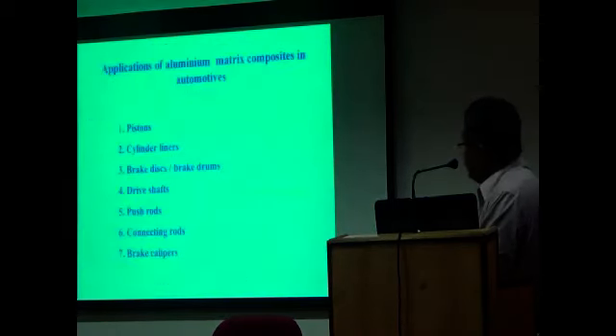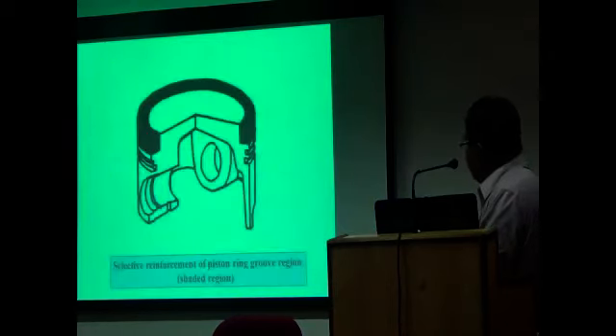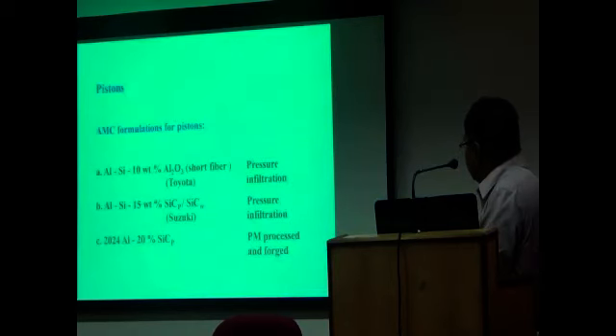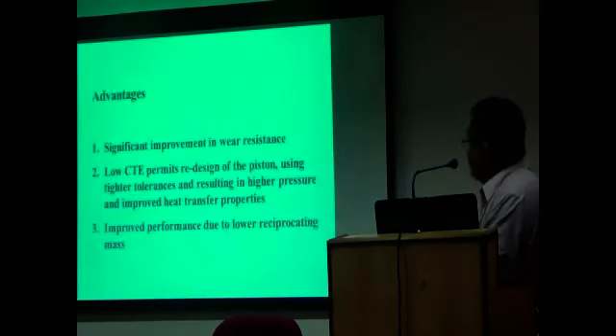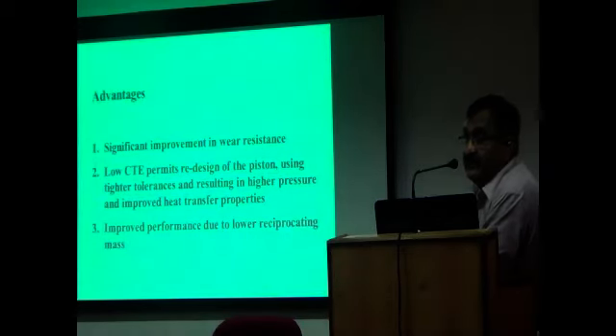I'll just show you the pictures of some of these. The pistons, cylinder liners. So this is a piston. When you have an aluminum ceramic either in the form of a skirt, in the top portion, ring portion, or the entire piston is made up of the MMCs, it has several advantages. These advantages are the following: significant improvement in wear resistance, and because of the low CTE, coefficient of expansion, of these aluminum composites, it allows redesign of the piston using tighter tolerances, resulting in higher pressure and improved heat transfer properties. Improved performance due to lower reciprocating inertia, and lesser fuel consumption. These are the advantages of aluminum composite pistons.